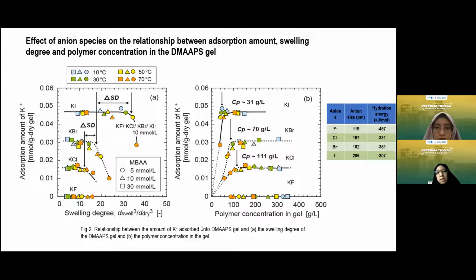When we see this figure, we can also convert it to the polymer concentrations. We can see that the adsorption amount remains unchanged for KI, at almost 31 gram per liter, and for KBr it increased to 70 gram per liter, and for KCl up to 111 gram per liter.